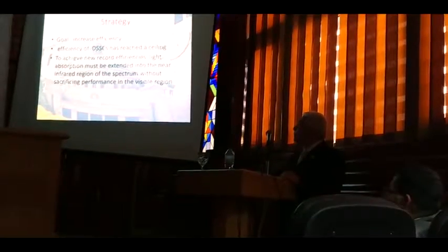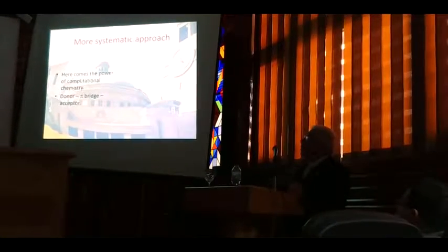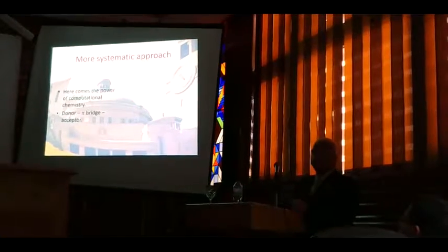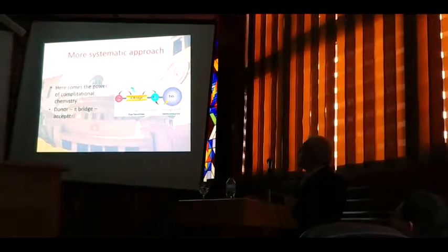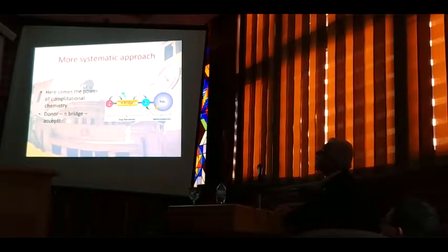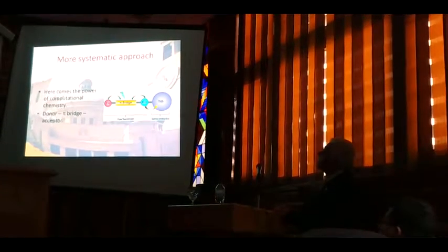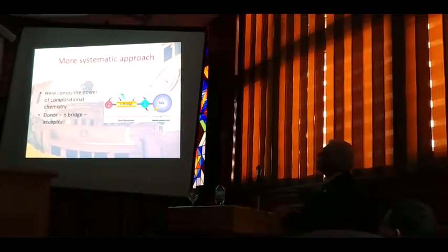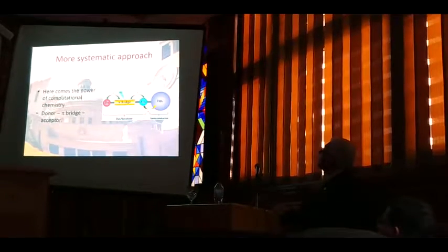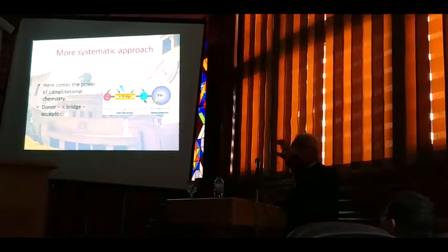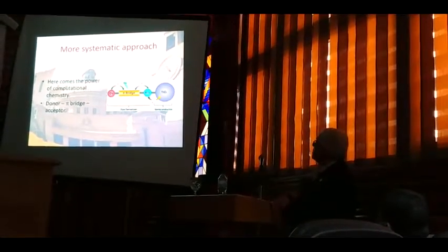Organic chemistry is fascinating in one thing: you can play a little bit, and they are very clever in preparing organic compounds. So this kind of dyes, which we call donor-bridge-acceptor. This is a donor, and this is a bridge, and this is the acceptor. The acceptor ends with an anchoring group, a group that can catch the titanium oxide surface.